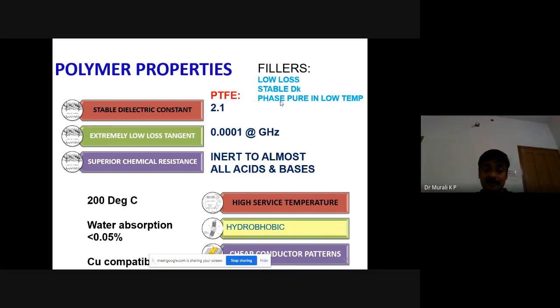You can see this with respect to the PTFE polymer, polytetrafluoroethylene, known as Teflon. These are the values: 2.1 dielectric constant, 0.0001 loss at 1 gigahertz, and as you know, PTFE is highly inert, it can be operated around 200 degrees without any problem, and water absorption is very low. It is compatible with copper.